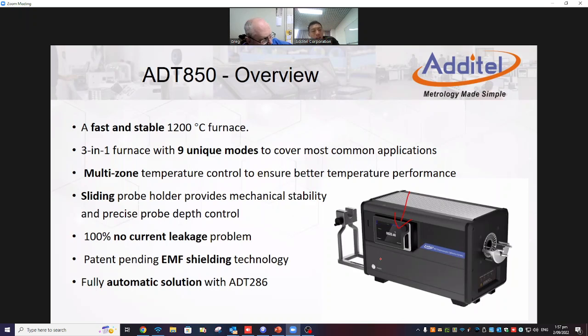One point where the ADT850 is better than the Fluke one is the cooling time. For the 911A, I think that's the Fluke one, they may need 3 hours, 180 minutes, to cool down from 1200 degrees Celsius to room temperature. But the ADT850, I remember it's just 90 minutes. So that's just half the time they need to wait. Okay. Yeah, pretty big advantage.